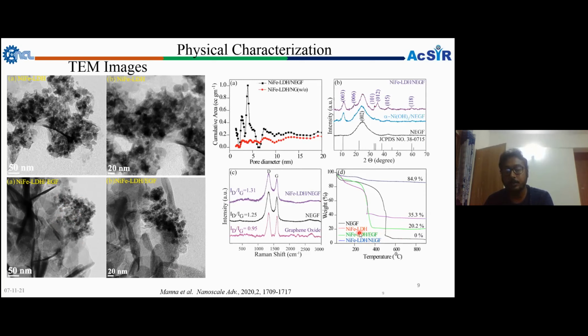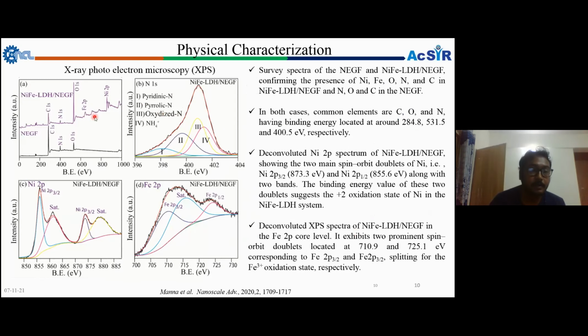So the morphology we confirmed, but their chemical environment and the presence of iron and nickel we confirm through X-ray photoelectron spectroscopic analysis. This is the survey spectra for the nitrogen doped entangled graphene framework. Here there are three peaks: an intense peak for carbon 1s, and two other peaks for nitrogen and oxygen. But after incorporating nickel iron layer double hydroxide over the nitrogen doped entangled graphene, additional peaks appear here, one for iron 2p and another for nickel 2p.